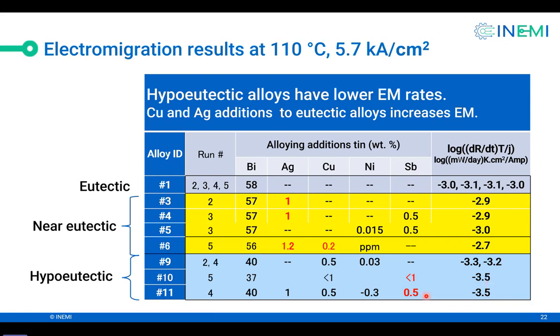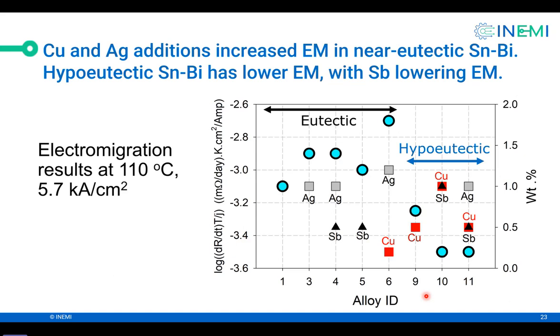Now these results are in tabular form, and I've shown you too much stuff on the table. So let's go to pictorial form, which might be easier to digest. In this plot, the vertical axis is log of rate of change of resistance times temperature over current density. The horizontal axis are the 8 alloys. Let's take alloy 1. The rate of electromigration is -3.1. This is a eutectic alloy, so alloy 1 is eutectic.